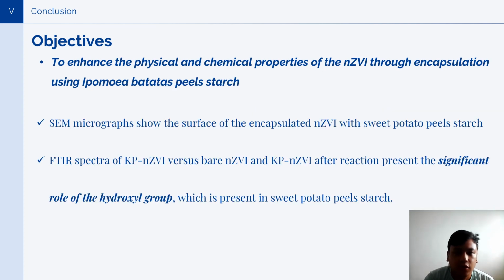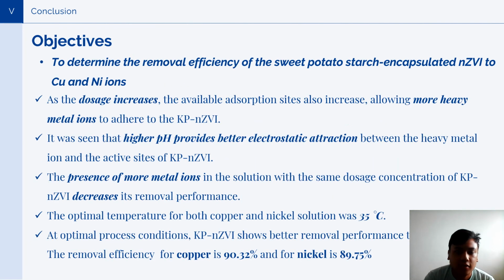Next is that the researchers were able to enhance the properties of the nZVI through encapsulation. The SEM micrographs have shown that the particles were encapsulated successfully with the potato peel starch. The FTIR spectra has also shown the significance of the hydroxyl group present in the sweet potato peel starch. Lastly, the researchers have obtained the optimal values for each parameter tested. At these optimal conditions, the maximum removal efficiency attained was 90.32% for copper and 89.75% for nickel.